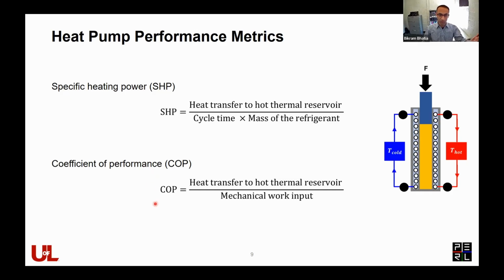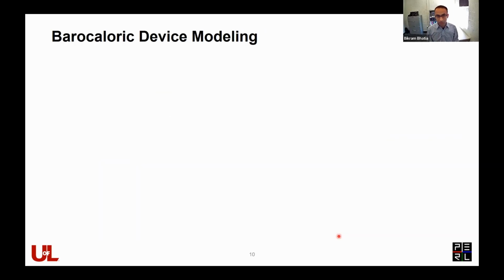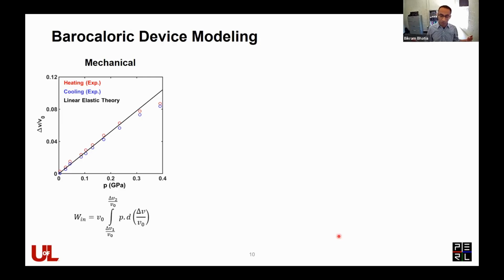And of course, we also look at the COP, which basically is the efficiency of the heat pump, which is again defined as the heat transfer to the thermal reservoir divided by the work input, which in this case is mechanical work, so pressure. So we first started off with modeling this device performance. We have three components. First is modeling the amount of work that we put into the refrigerant. So this is mechanical work going into the compression of the material. We can use linear elastic theory, and we compare the normalized volumetric change of the material as a function of applied pressure. And from there, we can figure out how much work we put in. That goes in the denominator of the COP equation.